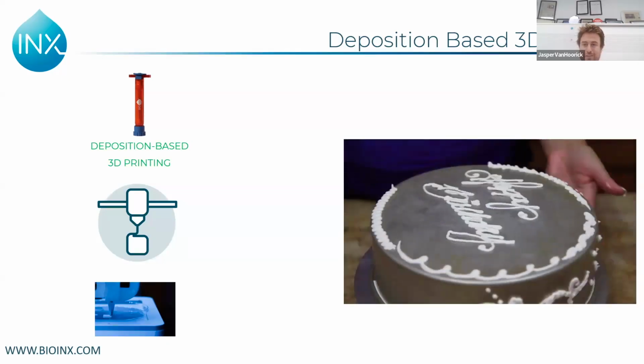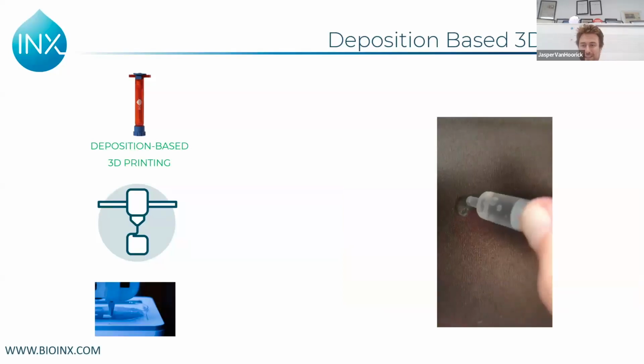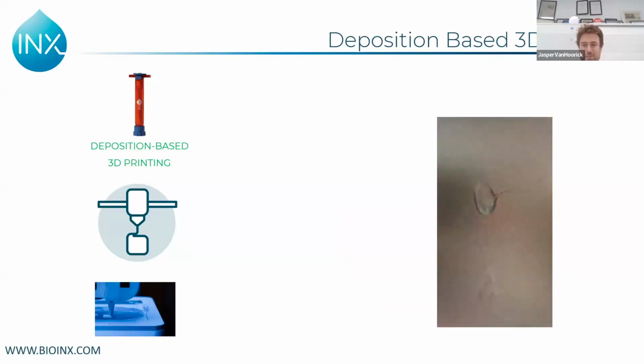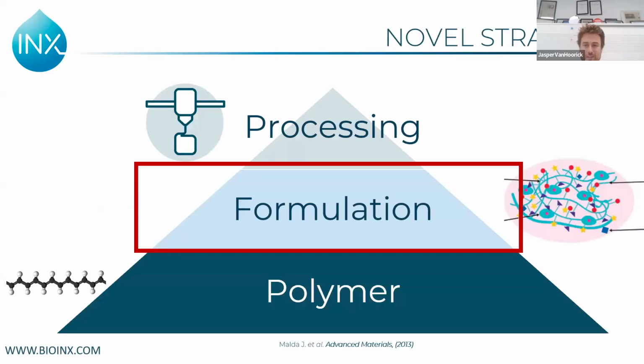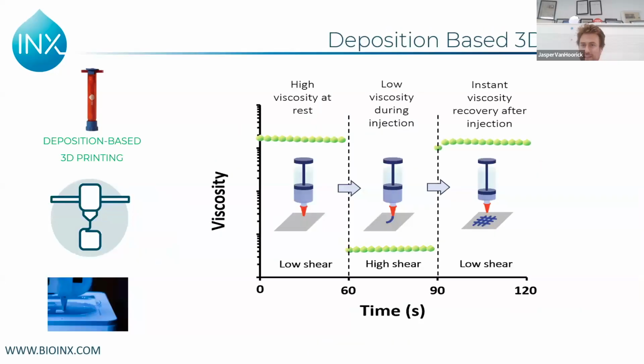Unfortunately, if you think about hydrogel, hydrated solutions, most of them behave like shampoo or water. If you extrude them, they will just keep on flowing, and you'll never be able to get a nice 3D structure out of it. Fortunately, we can get this behavior in there by playing around with the formulation. And then we get to materials which we call shear thinning materials, meaning that they have a high viscosity at rest. And if you put mechanical force on them, they become liquid. And once you remove this external mechanical force, the viscosity increases again, and they maintain their shape. Typical materials like that are toothpaste or hair gel, for example.